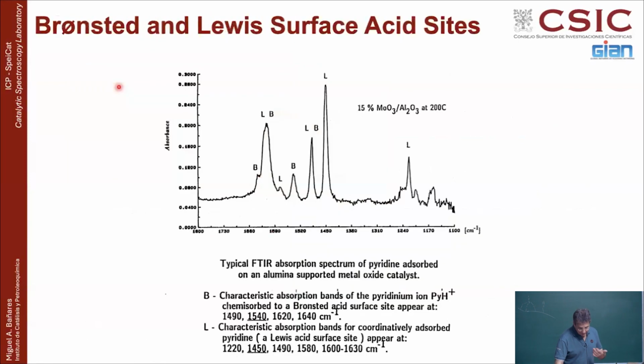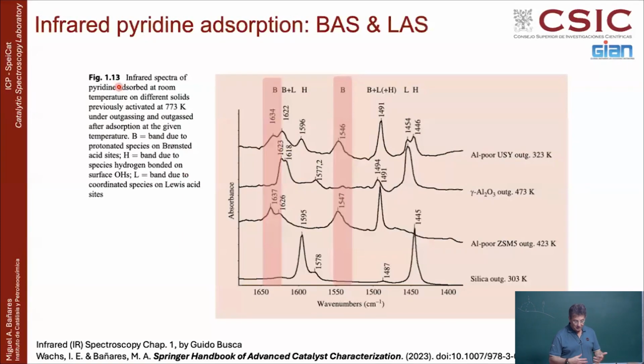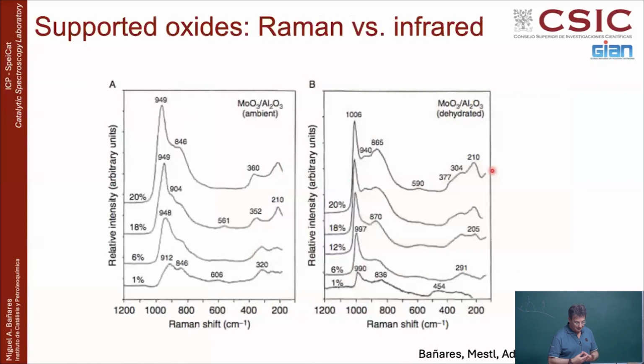So you can tell, okay, there is more Brønsted acidity on these materials just by looking at the hydroxyls. And again, the other alternative is, even if you want to go in more detail, you can adsorb pyridine, and the pyridine adsorption will show different vibration modes depending on whether they sit on Lewis sites or Brønsted sites. So it can tell you the distribution of these sites. And depending on the sample, you will see there is more Brønsted than Lewis or more Lewis than Brønsted. And then you can quantify how many sites, because you can quantify the chemical adsorption of this pyridine, and also the population distribution of these Brønsted and Lewis sites at the surface of these same materials I showed you before, only the hydroxyl groups like silica, ZSM5, gamma alumina, etc. So that is very important.